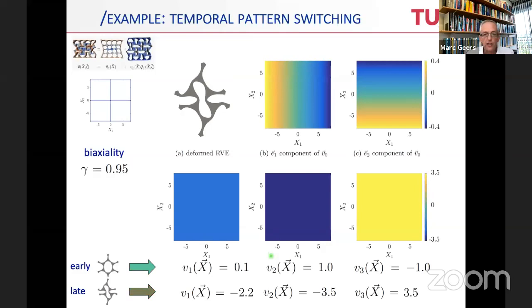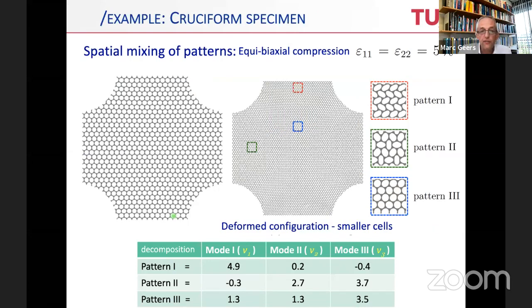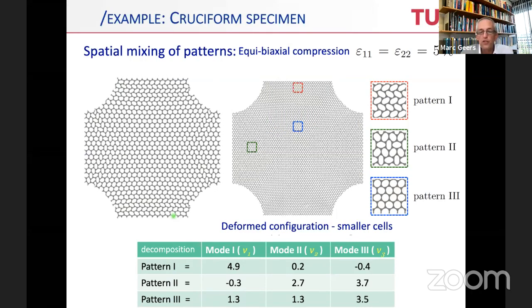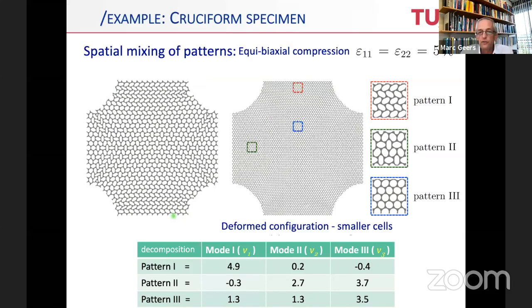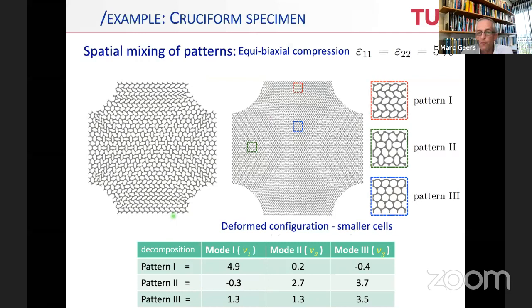If I go to the other biaxiality ratio, and now the one at the bottom is displayed here, I again see a clear contribution, -2.2 from mode 1, a negative 3.5 from mode 2, and a positive 3.5 from mode 3. And the linear combination of these three modes then again gives the pattern that has been observed in the different uniform state. Now, more interesting even is the spatial mixing of patterns, like in this cruciform specimen. So here we see the cruciform with an equibiaxial compression. It shows both pattern 1, pattern 2, and pattern 3. And again, you can see that the three patterns are in fact linear combinations of modes. You see the coefficients of the linear combination listed in this table. It's not really important, just remember they're linear combinations.